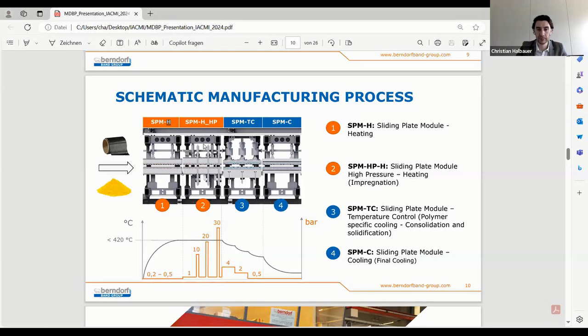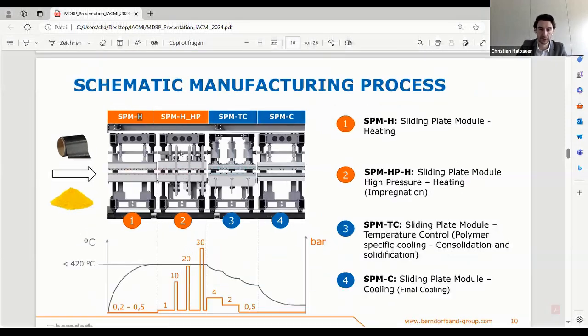Within our second module, as you can see here, we have different options to adjust either temperature or pressure, or in that case, both, because here you have the high pressure beams. At the surface of those beams, we can apply pressures of up to 50 bar. Next to them, you have different heating and pressure sections. They are independent from one another, which means you can set a temperature of, say, 400 degrees here, 420 here, and with different pressure levels. So it's fully adjustable. This is due to independently working cylinder equipment.